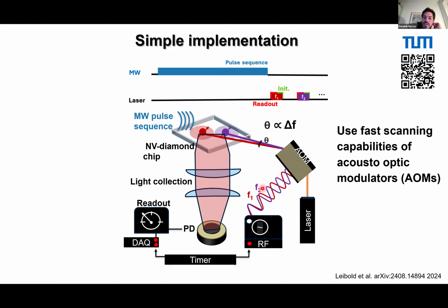But at the same time, we can just feed in different frequencies, and this basically leads to a deflection of the laser beam. And this basically happens, at least on the time scale I'm talking about, in real time. So this can happen in a few tens of nanoseconds. So we can move the laser spot very quickly from one position to the next one. In this case, if we have only two readouts, by just putting in two frequencies.